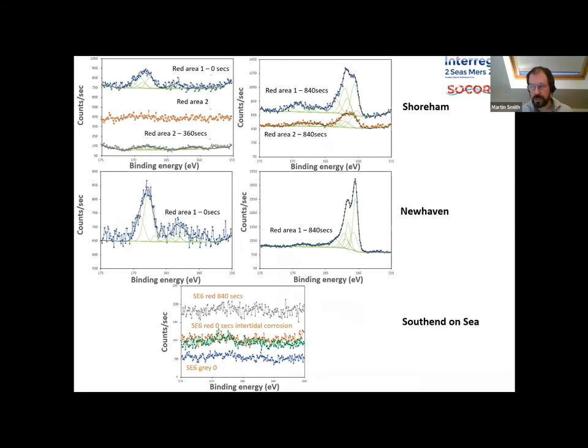So that's data we originally collected at Shoreham. We've now expanded on this in more recent projects at SOCORRO, but we can see the same phenomena going on in different samples and across different sites. So at Shoreham, we see outer surfaces with high concentrations of sulfate and intermediate oxidation state sulfur compounds. We see mackinawite and pyrite, monosulfide and disulfide, against the steel surface. We see the same sort of compositional change at New Haven.